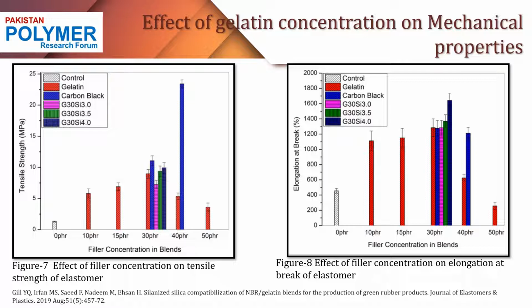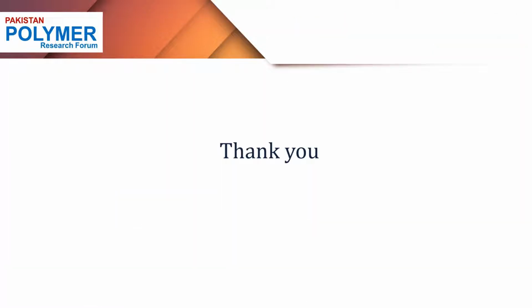But again, the salinized silica acting as a compatibilizer forms specific bonds with the rubber and the gelatin that improve the mechanical properties in cross-link density and hardness values. All these results of this research depicted that increasing concentration of gelatin causes an increase in the mechanical properties and improvement in the mechanical and cross-link density performance of the elastomers.